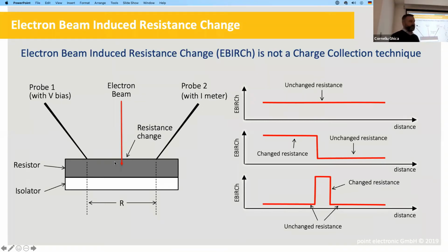So if there is a weakness in a device, and let's keep that general, then the electron beam is sometimes able to change the local resistance of that weakness. And what would happen is that as we keep a constant voltage across the probes, we would see a change in current because there's a change in resistance. So again, as you scan from left to right, if the material is perfect and is not responding to any changes in the electron beam, then we'll see no contrast. If there are grains that are sensitive to the electron beam, perhaps in different amounts, then we should see those grains in the image as well. And then if there is a spot, then that shows up in the image.